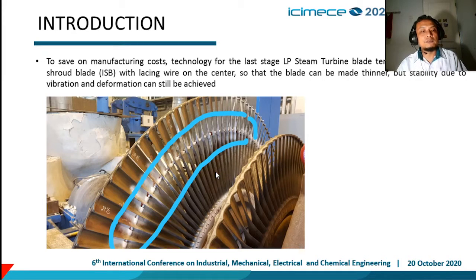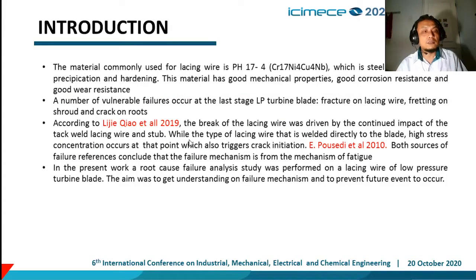To save on manufacturing costs, technology for the last stage low pressure steam turbine blade tends to use an integral shroud blade, or ISB, with a lacing wire on the center so that the blade can be made thinner but stability due to vibration and deformation can still be achieved. The material commonly used for lacing wire is PH17-4, which is a steel with martensitic precipitation hardening. This material has good mechanical properties, good corrosion resistance, and good wear resistance.